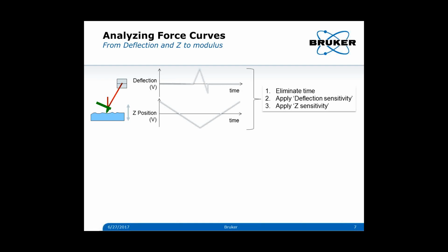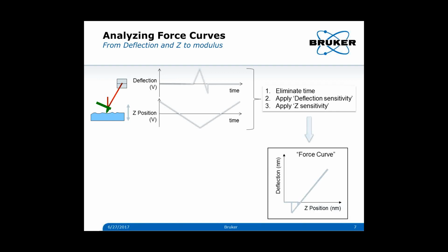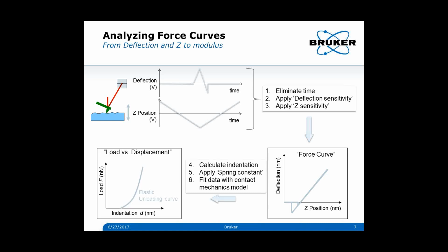Now, if we eliminate time out of this, then we can convert this into a force curve, which is deflection versus Z position. If we subtract off the deflection from the Z position, we can get an indentation, and then we can get a load versus displacement curve, which is essentially the same as what you would get with a nano indenter. And that can be fit with an elastic model. So that's how we get our modulus out of the measurement.